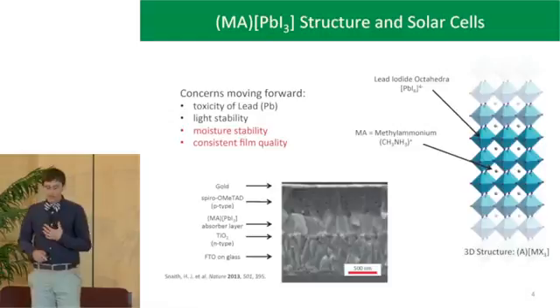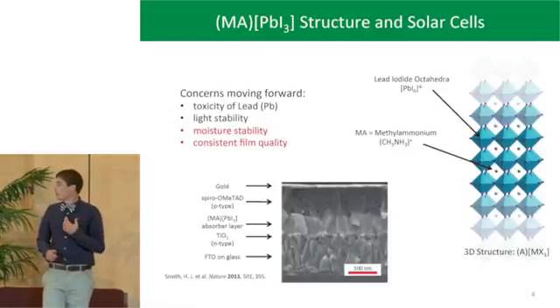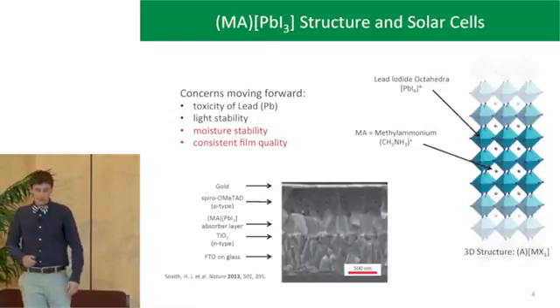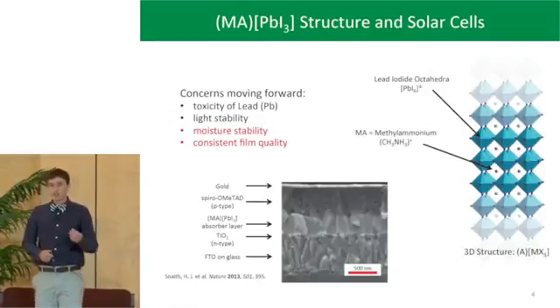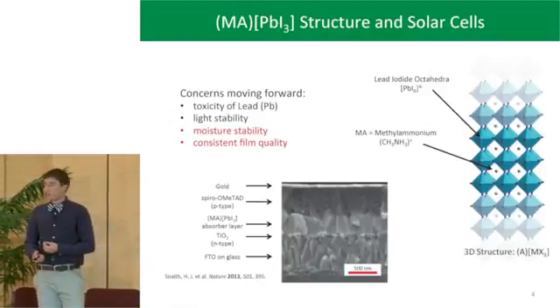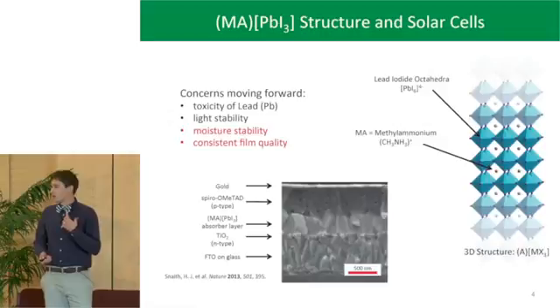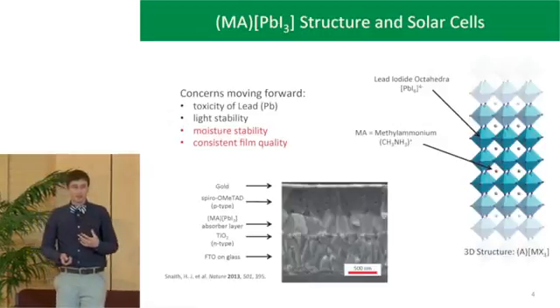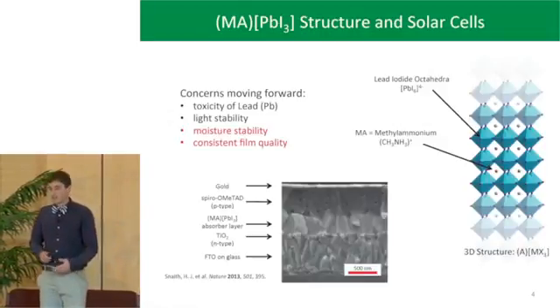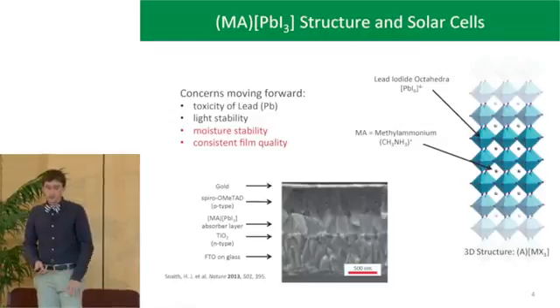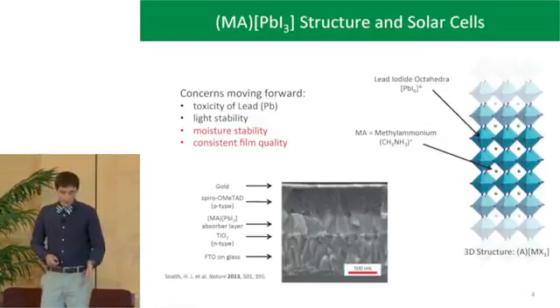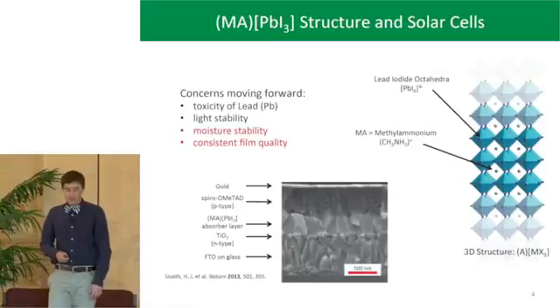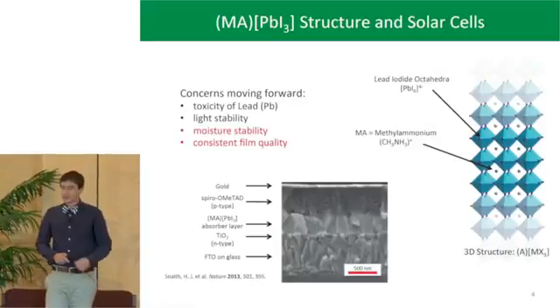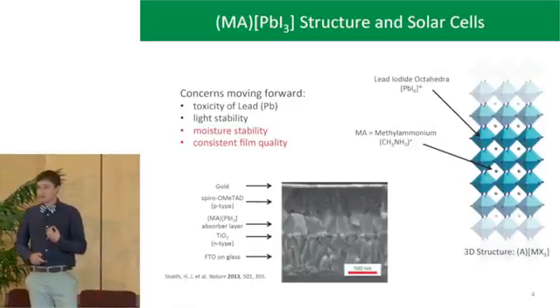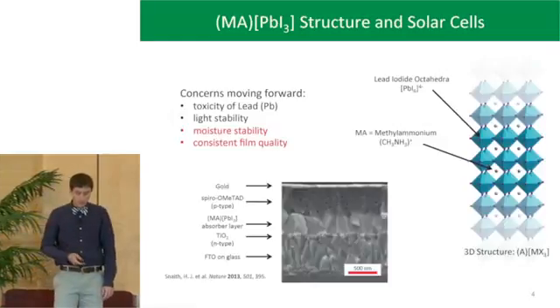This material is very nice. It has a very good band gap for solar cells, around 1.6 eV. And it's a direct band gap absorber, which means that it absorbs a lot of light for a very small amount of material. So because of that, you can form thin film devices. And this is an example of an architecture here for a device. However, it's not perfect. There are some concerns that we have to address before we move forward with it.